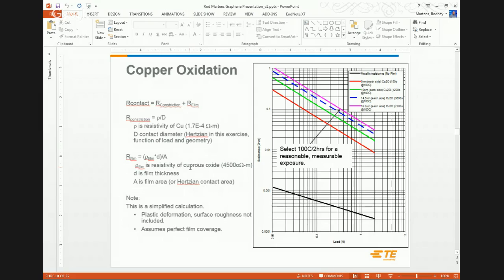Now, once we start adding a film in there, once again, we have to consider the resistivity of the film, the thickness of the film, as well as the area in contact, and that would be either rho times d over A. So we'll add that in series with the constriction resistance, and I plotted in a few different film thicknesses corresponding to a few different growths, and chose one that would give us an order of magnitude or two above the clean condition, but still well within our measurable range.